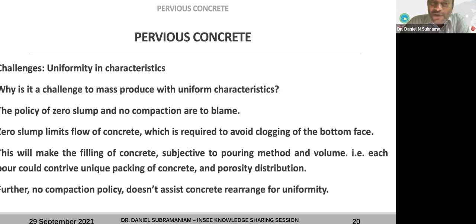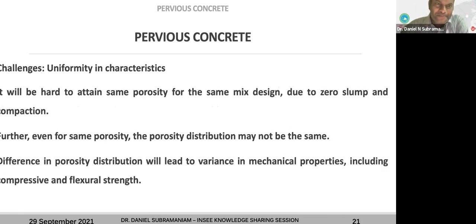The zero slump limits flow of concrete, which is required to avoid clogging of the bottom face. I think I have spoken about these. The other important thing is that because we have a no compaction policy, and also the slump is zero, the aggregates don't get rearranged. The way you pour it, it'll stick. You can just think about that: when you pour it into something, it will just stay like that. It's not going to move about or rearrange. That is the actual cause for the non-uniformity. And it will be hard to attain the same porosity from the same mix design due to zero slump and compaction. I have spoken a lot about this.